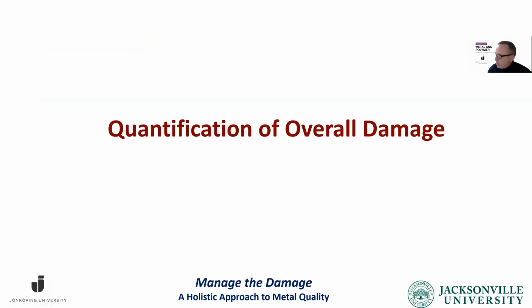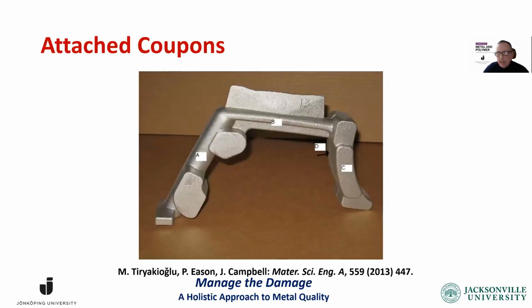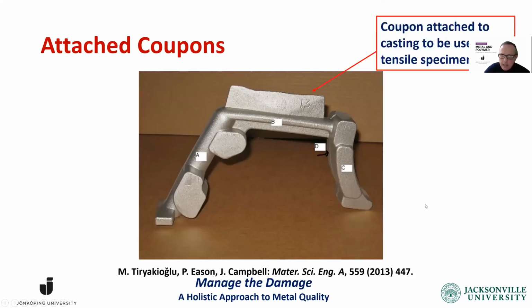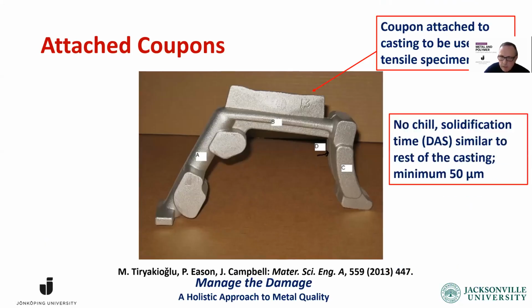So I'm coming toward the end. How do we quantify the overall damage? Just have a little extra area in your casting. It's common practice in aerospace. There's a coupon attached to the casting. You cut it off and you excise a specimen and you run a tensile test. You don't need to chill it. It needs to solidify under the same conditions. It gives excellent information about the quality, the outgoing quality of your production system.